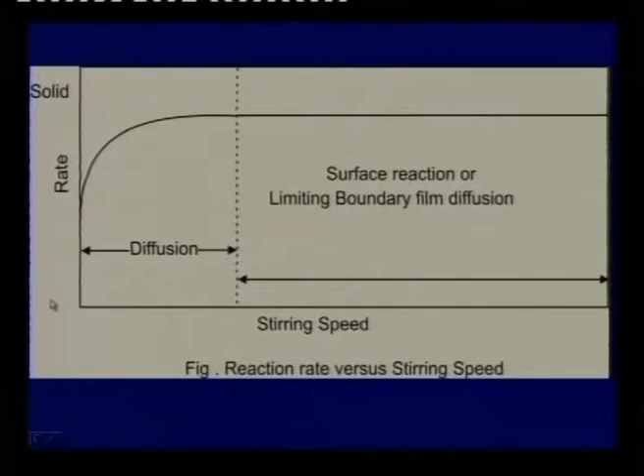We discussed this a little more from the kinetic point of view, that any leaching reaction can be expedited by stirring, because there is a concentration profile at the surface and there is a concept of boundary layer, where say 99% of the concentration change takes place. So, if you stir the solution, the concentration profile is made steeper, because the boundary layer becomes thinner as the stirring speed increases. But in this case, if you plot the stirring speed against rate, we find that beyond a certain stirring speed, the rate of diffusion cannot increase, because the boundary layer thickness has been reduced to the minimum. So, then only temperature will have to be increased.